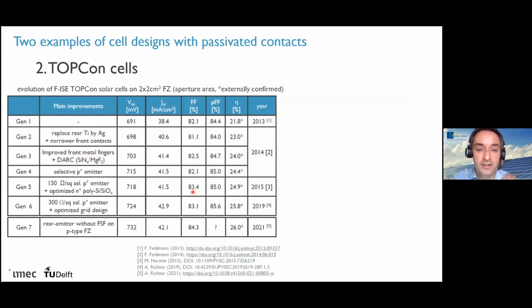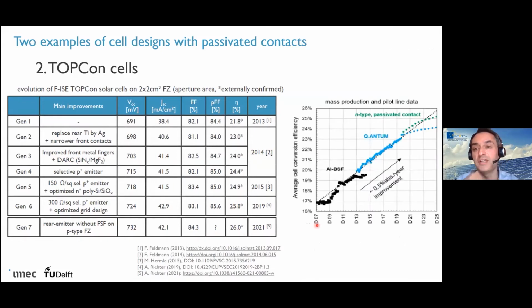Also here, over the years, very high efficiencies of around 26%, both on N-type and P-type wafers, have actually been reached. Some companies are already trying to produce it in their production lines. We can again look at the example of Hanwha Q Cells: we had the black dots, the aluminum BSF; the blue dots, the PERC cell, which stagnates again around 24%. Now they are starting to produce these Topcon devices too, and you can see they can reach around 25% in production. So some early adopters are already trying to really produce this in very large quantities.